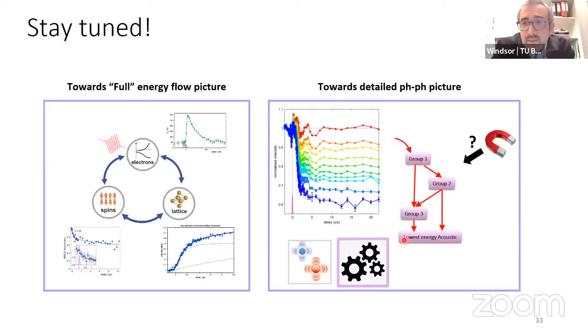So this experiment is not done with wave vector resolution. We're not looking at specific phonons. In essence, we're not limited, quote unquote, to the phonon picture, in the sense that what we extract from a diffraction experiment is a quantity that tells us how much the atoms are vibrating. Now, different atoms vibrate differently at different temperatures. This is a completely static description. It comes out when you solve the crystal structure using neutron scattering or so, you get a Debye-Waller factor, which tells you the mean square displacement for that specific temperature. Now, this can then be mapped onto the phonon population, but we do not directly probe specific phonon modes unless we have a specific situation where we have the beating of a coherent phonon, which was apparent here.